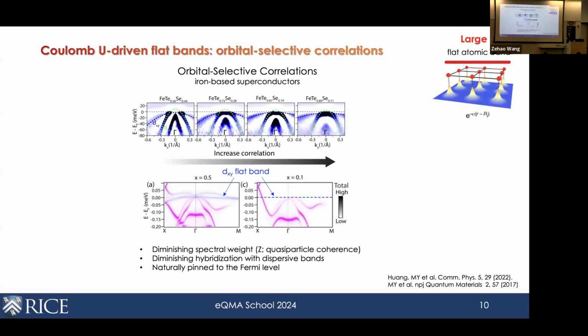So what I'm showing you here on top is ARPES data taken on this iron, tellurium, selenium. And from left to right is the band dispersions around the gamma point shown when you vary the ratio of tellurium versus selenium. So here, what's under these dotted lines are the bands around the hole pocket. And as we know that the curvature of these bands is inversely proportional to the mass, you can visibly see that this blue one, which I labeled XY, is a band that has visibly flattened as you go from one end to the other.